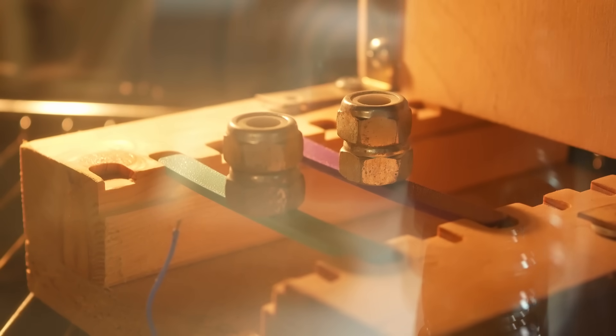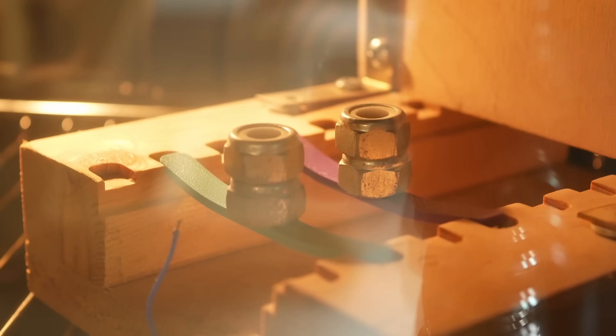The bars quickly became soft and you are definitely not able to use them anymore over 60 degrees Celsius. At 65 degrees Celsius, both failed just at the same time. So for the Polymaker material, the modified PLA is no more temperature resistant than the simple PolyLite PLA and that's also probably true for most other PLA plus or tough PLAs.